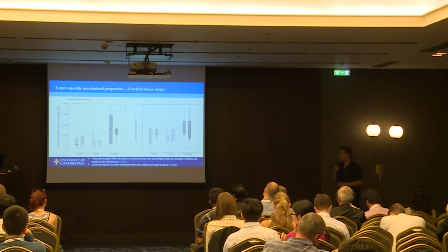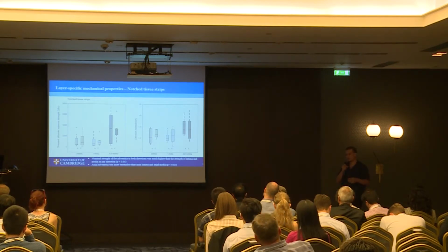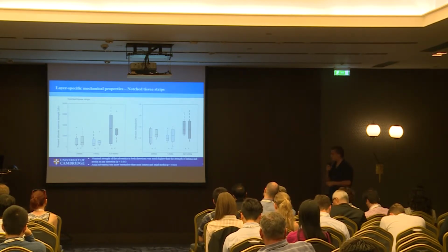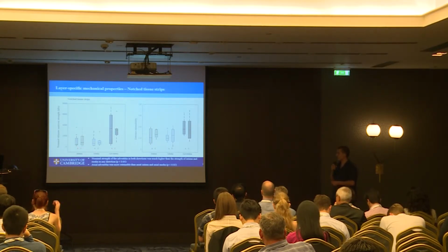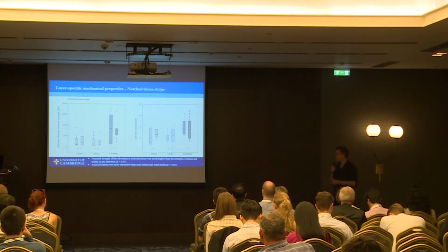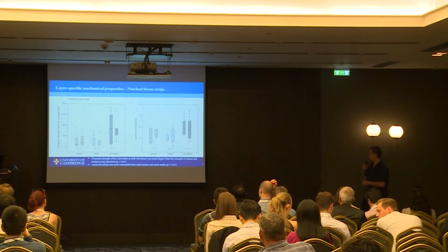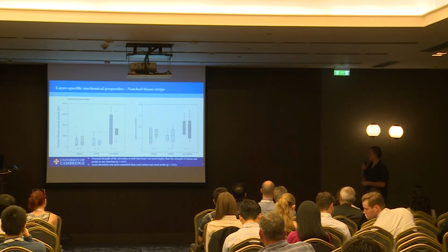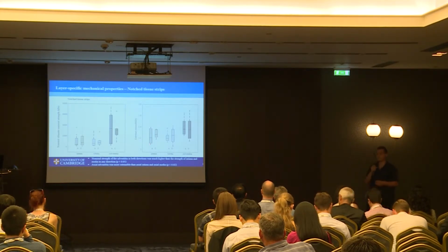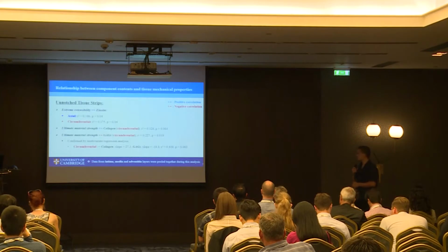This is mainly because we also saw in the preparation of the tissue samples that adventitia was largely untouched by disease, where the intima and media layers were highly affected and infiltrated with lipid deposits. And the fiber microstructures seem to be disturbed a lot compared to the adventitia. We also saw that the axial adventitia was more extensible than both axial intima and media, and this was the only significant result from the extreme extensibility component.